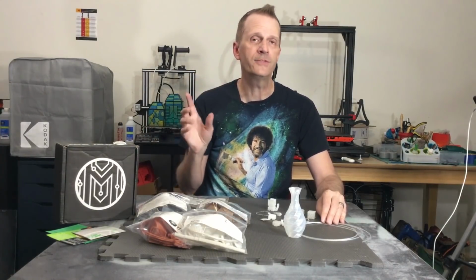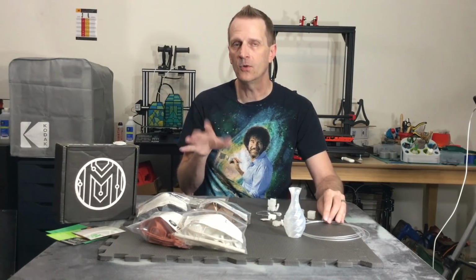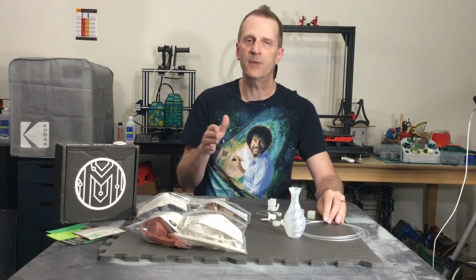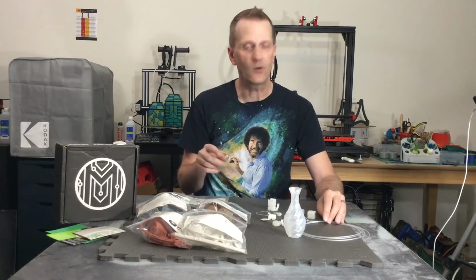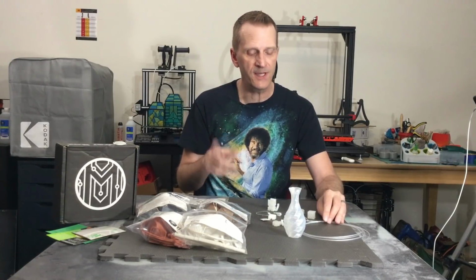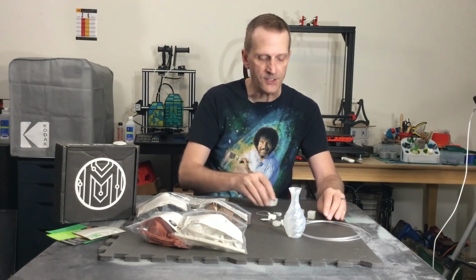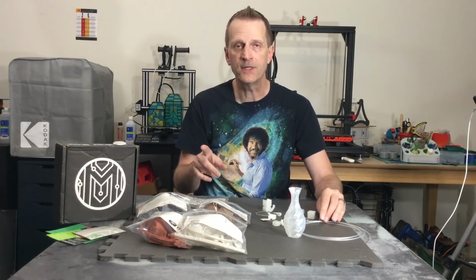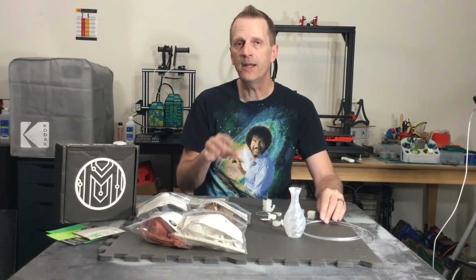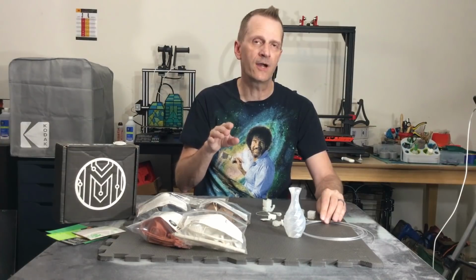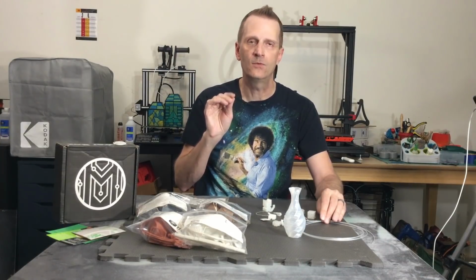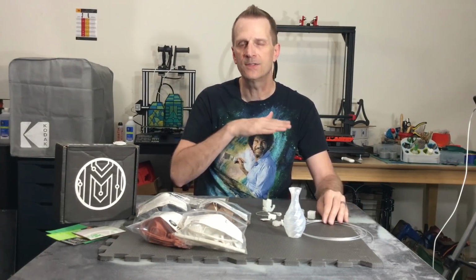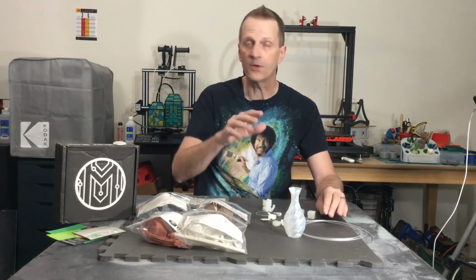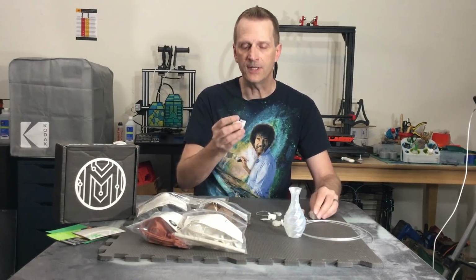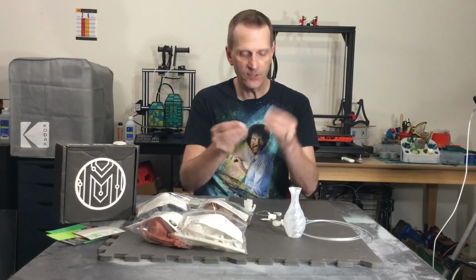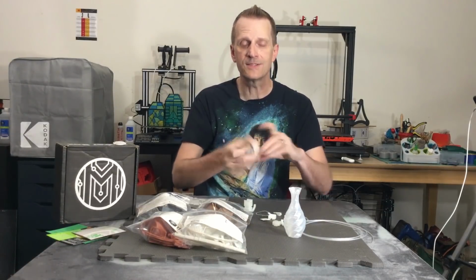Okay, so I also turned the cooling fan from my usual multiple step up to 40% down to 0, because it did say that, and that might have been my mistake. I did get some good bed adhesion at 238 degrees on the hot end with the heated bed at 50 degrees C to start, turn off the heated bed after about 5 or 6 layers, and just let the residual heat seep through the model. It printed. We were able to get a successful print. It printed out in one piece.